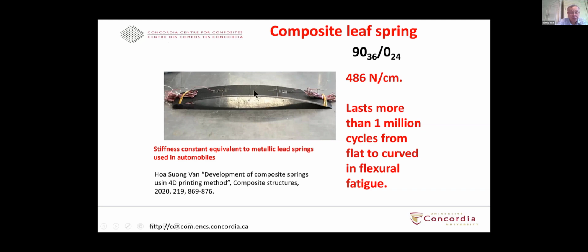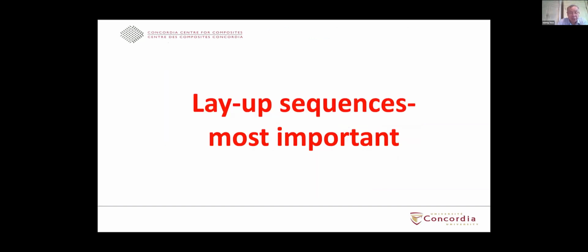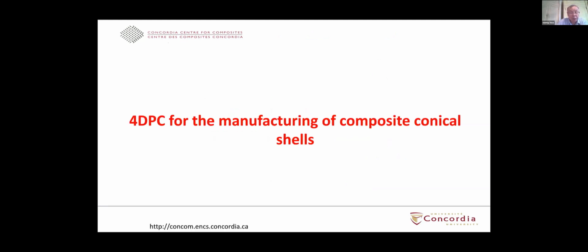We also subjected this leaf spring to fatigue loading. That means we press it down to be flat, and we relax it to be curved, up and down through more than 1 million cycles, and there is no sign of degradation. So it can really be subjected to fatigue load, and it has a practical stiffness value that can be used. The thing that I want to mention is that the layup sequence is most important.